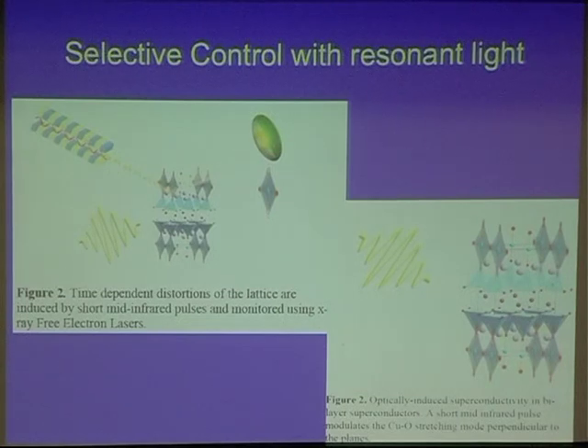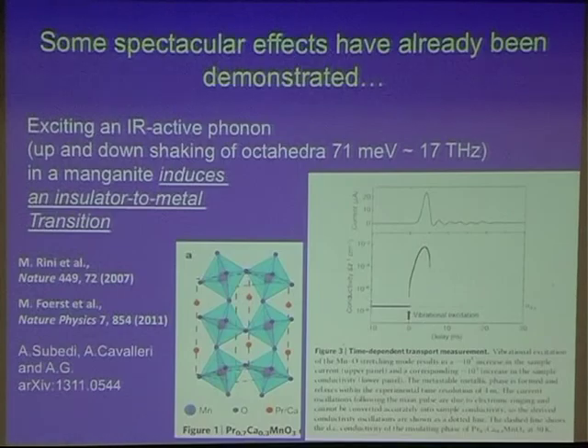The second route is this selective control with resonant light. What is the idea there? The idea is to use a laser pump which is able to excite some specific structural mode. For example, take a copper oxide and shake the copper oxygen octahedron like this, which these people know how to do with their lasers. And what one finds is that this triggers a structural change of the whole system into a transient new phase, which will have different physical properties. Of course, when you remove the laser light, you go back, possibly, to the previous state, but you could imagine pumping the system continuously to induce a new physical property.